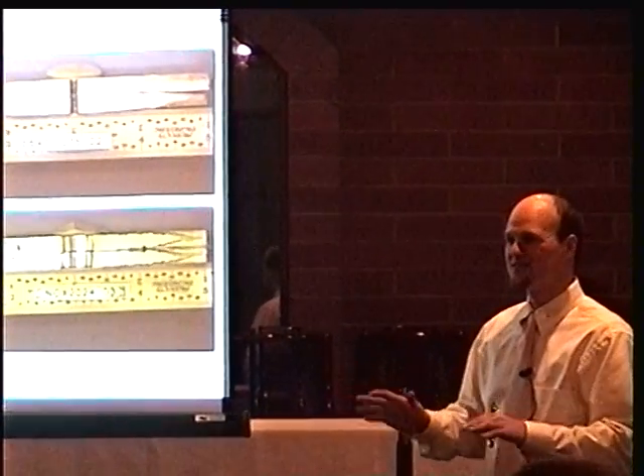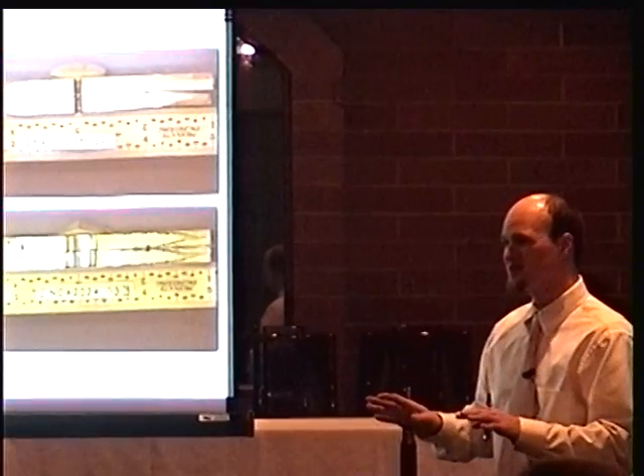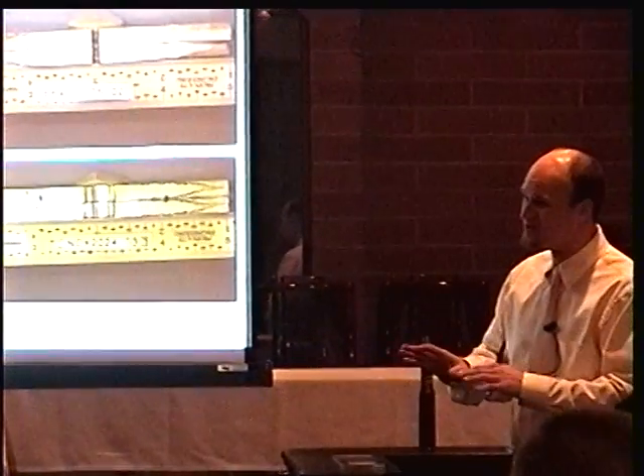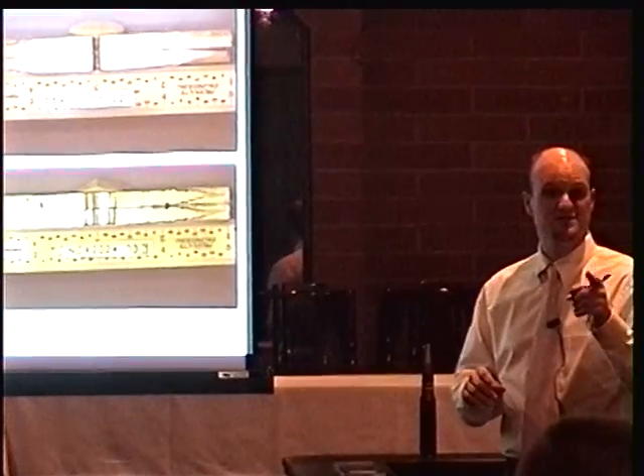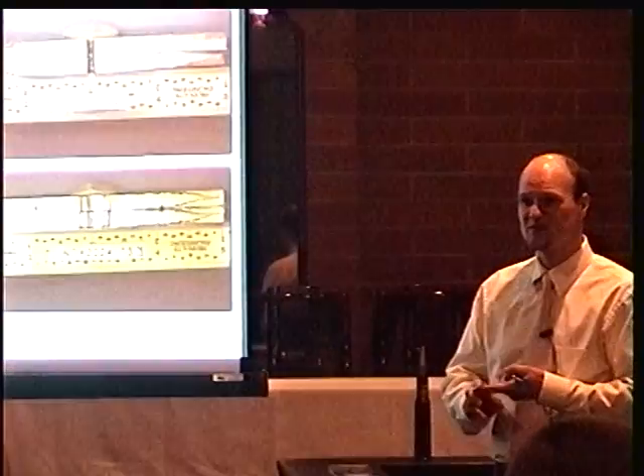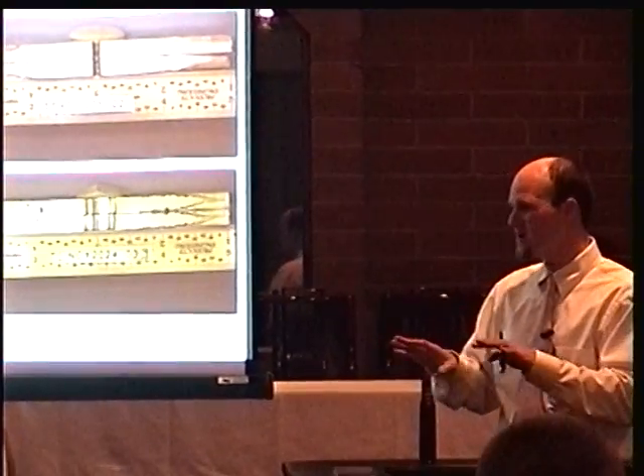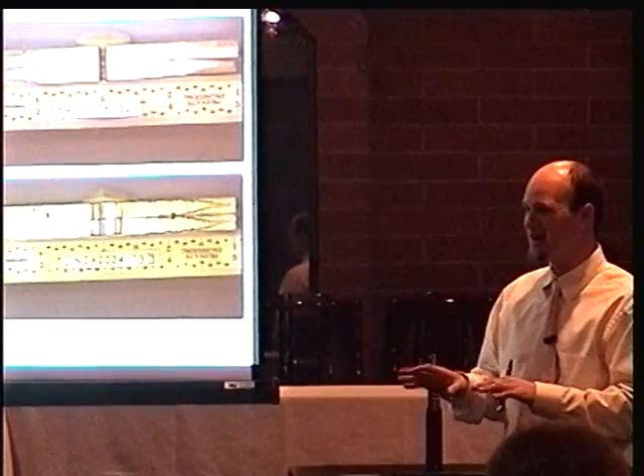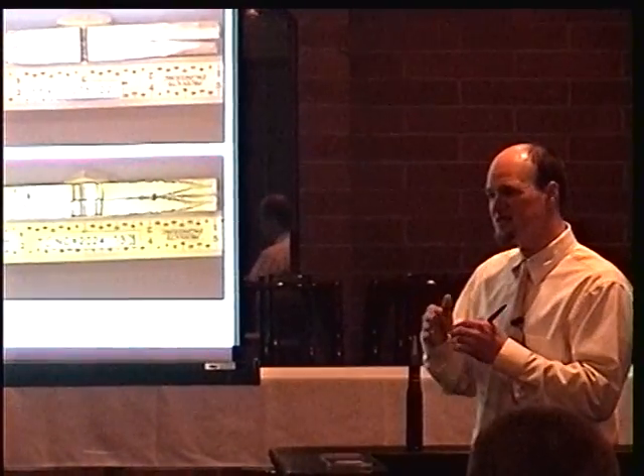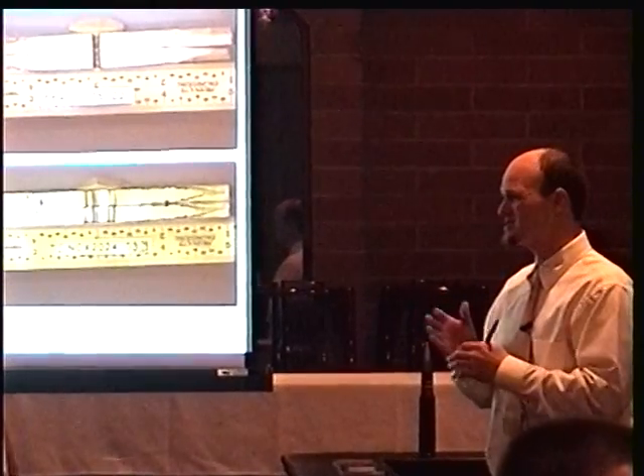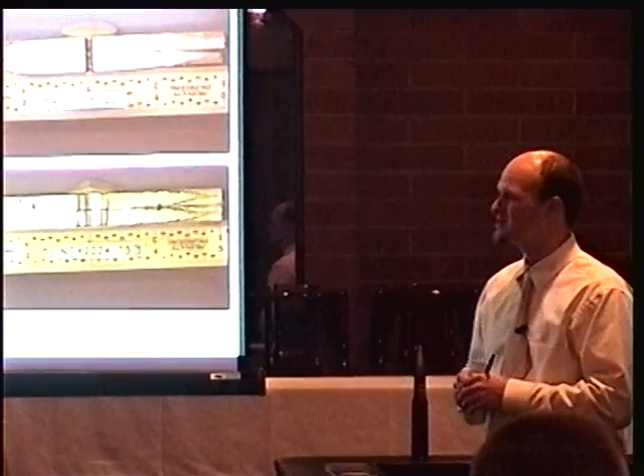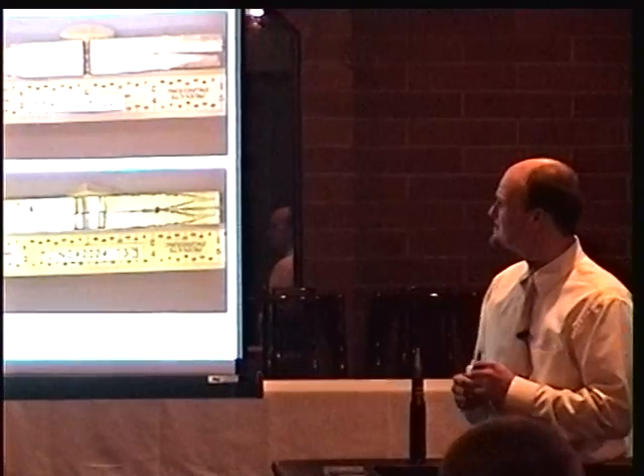They're very flat, not a lot of features, typical of what you would expect. There's not a lot going on. I passed some non-cold works around and some cold work specimens around. You can see there's not a lot going on. It's pretty flat, and typically you see this nice symmetric corner crack transition to a through crack. So it fits fairly close with how we're trying to model things. Next slide. And so here's some more pictures. You guys have seen this, but there's not a lot going on. These are some more non-cold work specimens. Can we go to the next slide?